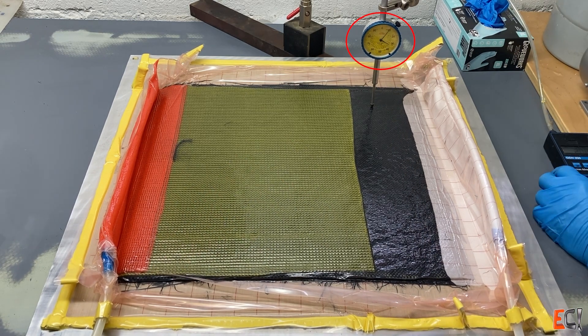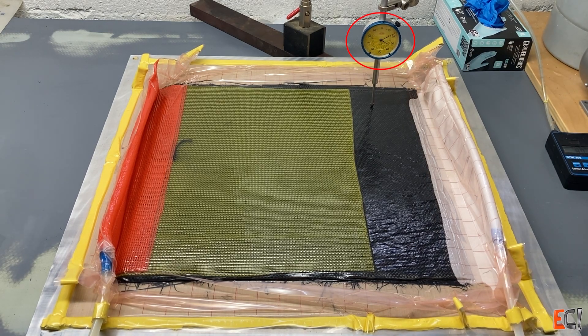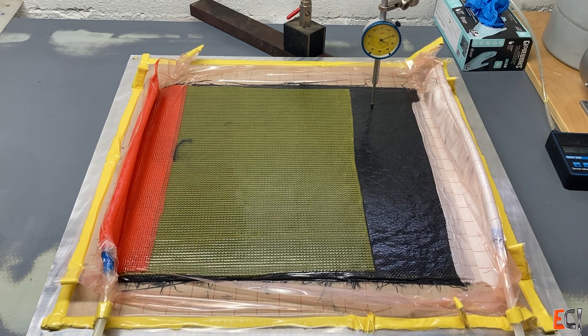That's totally fine and normal. But I'm trying to see if this does it a lot or a little. You can see as that flow front passes there, the needle is going to move to the right. That's not a terrible amount. It's probably around 10% of the total thickness, which is very reasonable. I was just interested to see if it would be more with this material.